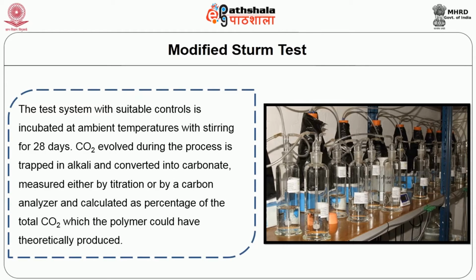Then the test system, with a suitable control, is incubated at ambient temperature with stirring for 28 days. Carbon dioxide is evolved during the process and is trapped in an alkali and converted into carbonate. This carbonate is measured either by titration or by a carbon analyzer and calculated as a percentage of the total carbon dioxide which the polymer could have theoretically produced.